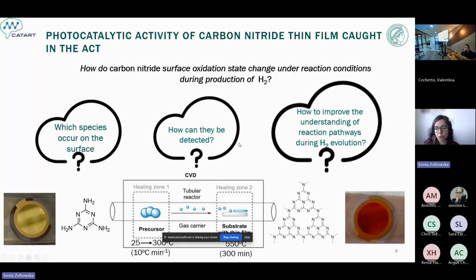In this case it was the gold chip, and we heat the substrate to 550 degrees Celsius. Then subsequently we heat the precursor to 300 degrees Celsius to avoid sublimation, and thanks to that we form a beautiful, very flat film on the surface of the gold, and also visibly you can see the change because the substrate changed from gold to that color.